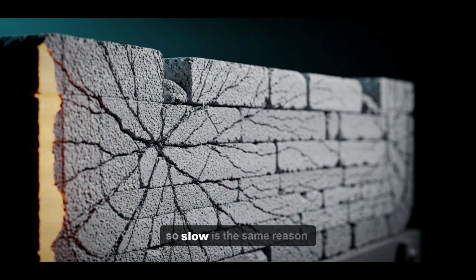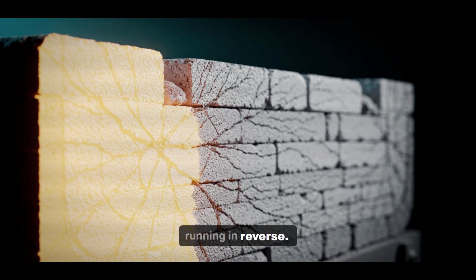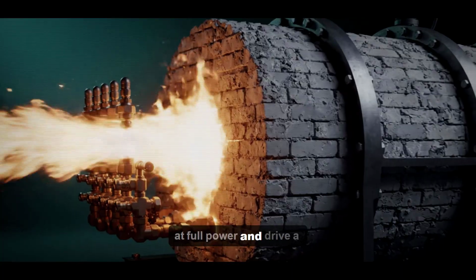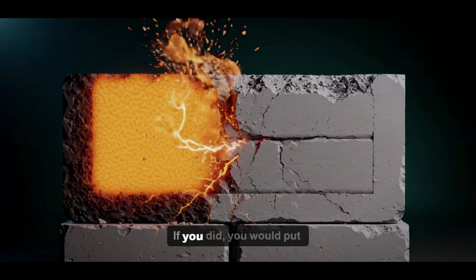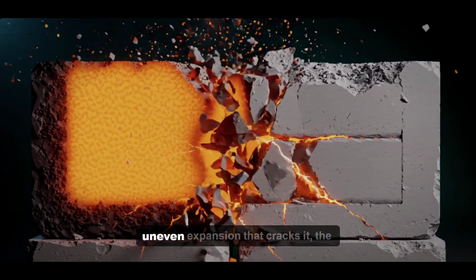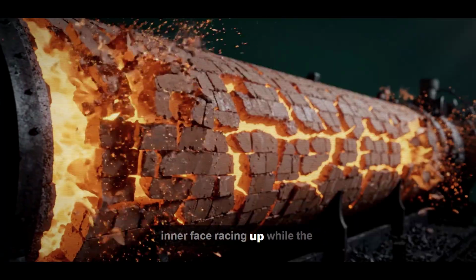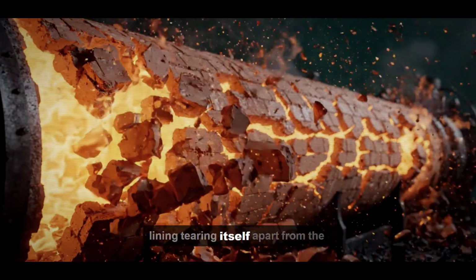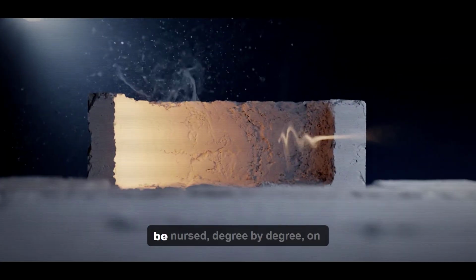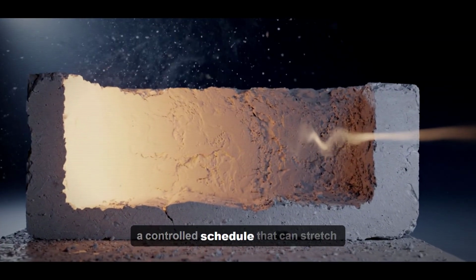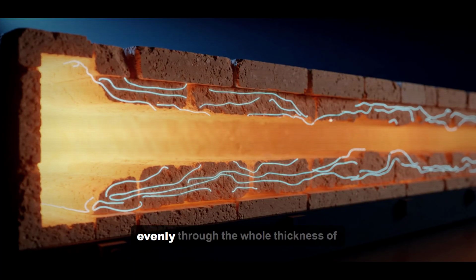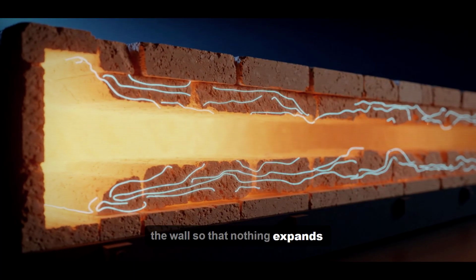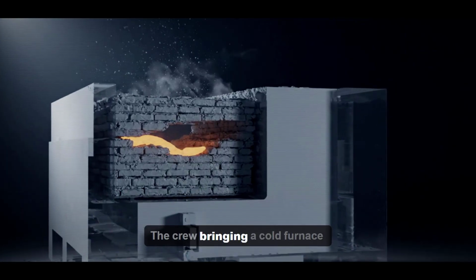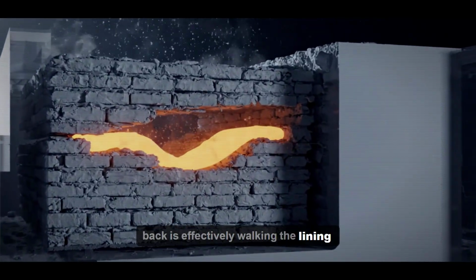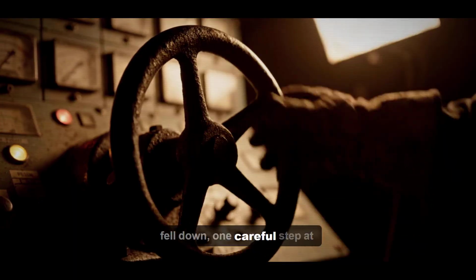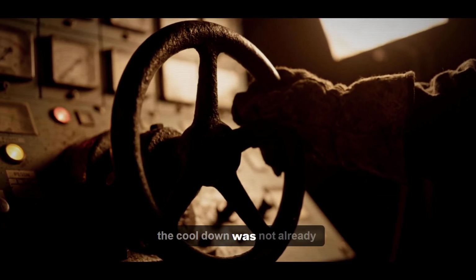And the reason the reheat is so slow is the same reason the cooldown was so damaging running in reverse. You cannot just relight the burners at full power and drive a cold lining back up to temperature in a day. If you did, you would put the brick through exactly the violent, uneven expansion that cracks it, the inner face racing up while the deep wall lags behind, the whole lining tearing itself apart from the inside. So the reheat has to be nursed, degree by degree, on a controlled schedule that can stretch over days, letting the heat soak evenly through the whole thickness of the wall so that nothing expands faster than anything next to it. The crew bringing a cold furnace back is effectively walking the lining back up the same cliff it fell down, one careful step at a time, hoping the damage from the cooldown was not already too much.